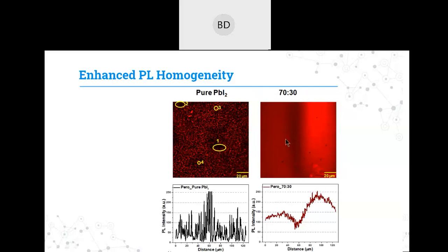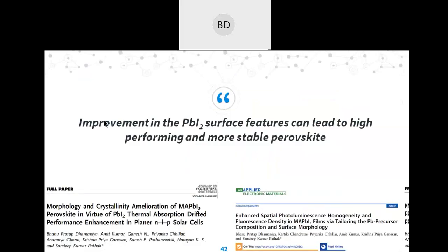Although we saw that there is some difference, that this part is a little bit less bright and this part is more bright, that may be due to some kind of electronic disorders present in the film, but which can be resolved even after some optimization processes. So with this process, we understood that PbI2 surface morphology has a very important role in governing the perovskite morphology. If you have a very good PbI2 morphology, then it will lead to a better performing and more stable perovskite.